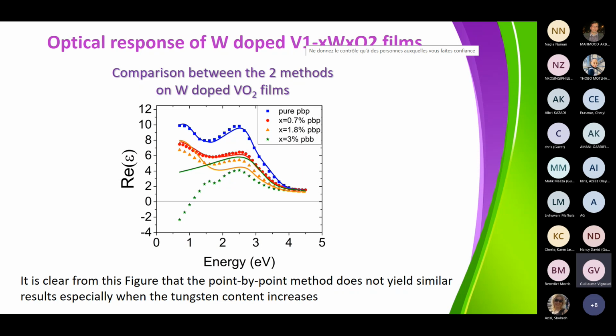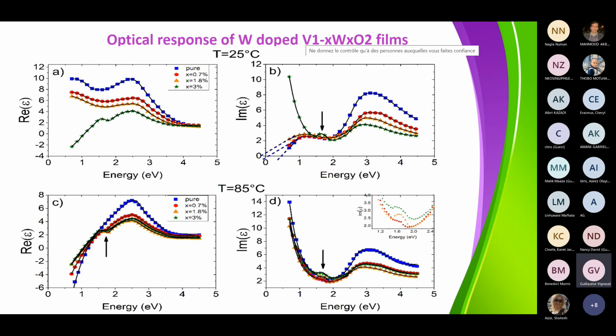You always have a mixture of monoclinic and rutile phase if you are doping with tungsten at a high level. Okay. So that's what we did. And then, you can see that if you look at 25°, the real part of the dielectric function is evolving like this. In the case of the 3%, it's evolving like that. And we can calculate this with the Tauc-Lorentz and Drude model.